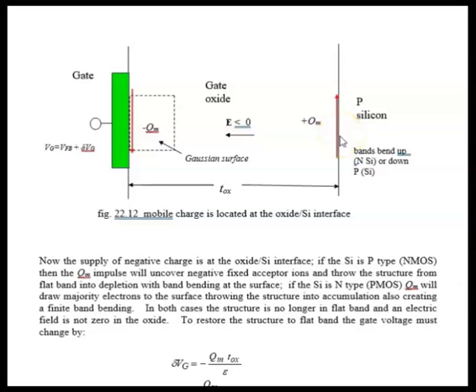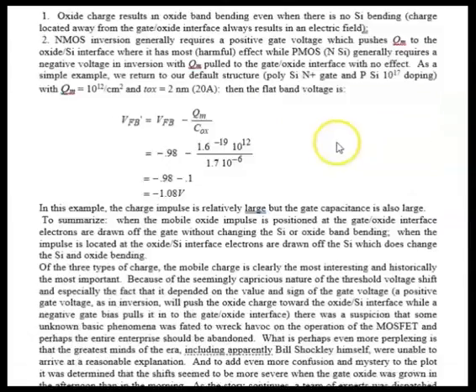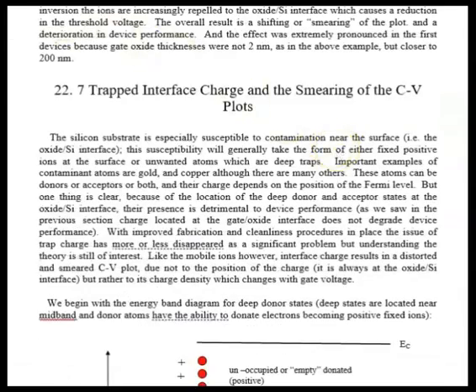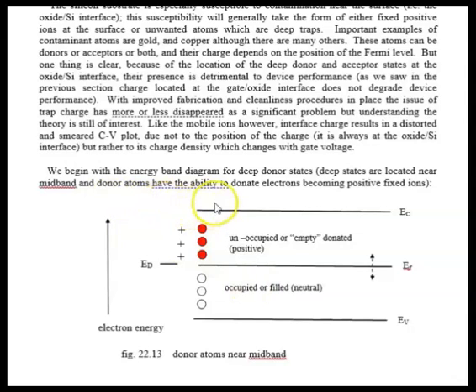And the difference between trapped charges and mobile charges is that the number of traps, the number of charges at the interface varies according to the position of the Fermi level. So that's what we want to talk about now. And we'll do that with a number of energy band diagrams. We start with an energy band diagram which has what we call deep donor states. Shallow donor states, the donor level would be right up here, about 60 to 80 millivolts below the conduction band. If it's a deep donor, the donor state would be somewhere close to or at midband.